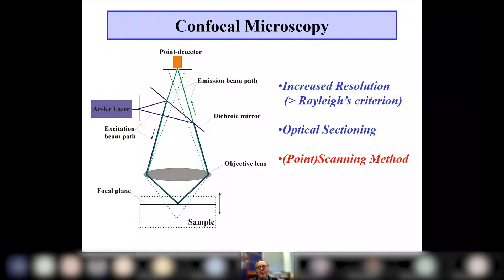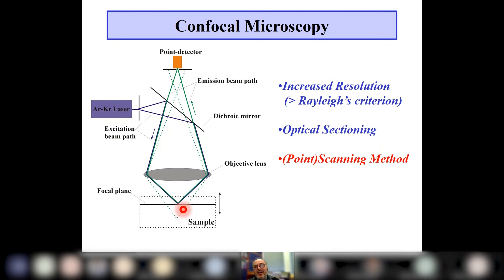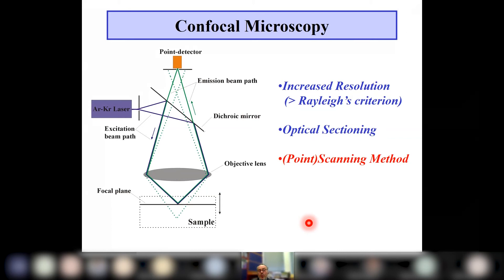Confocal microscopy is essentially a spatial filter where a point source of light is focused by an objective lens using the highest numerical aperture lenses available. The numerical aperture — a measure of the divergence of the light beam — can reach about 1.4, giving a diffraction-limited spot of about 200 nanometers diameter. Light below or above the focal plane is strongly discriminated against because both a point source and a pinhole in the detection scheme are used. You image one point at a time and must scan.